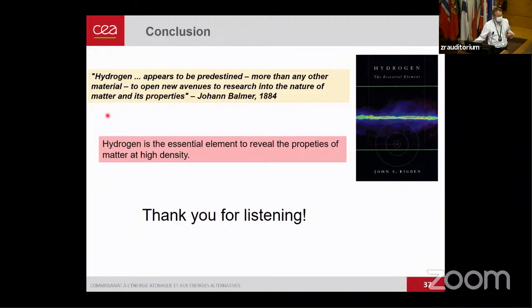A question from Kamil Dziubek. I understood you perform your infrared experiments for hydrogen and deuterium metallization at the same temperature. Is there any experimental evidence that the phase boundaries of the transitions between phase 3 and metal for both hydrogen and deuterium are almost vertical with T, as you have shown on the phase diagram? In fact, I didn't show that they were vertical. They are slightly increasing with temperature, but we have preliminary measurements. I'm not going to comment on that.